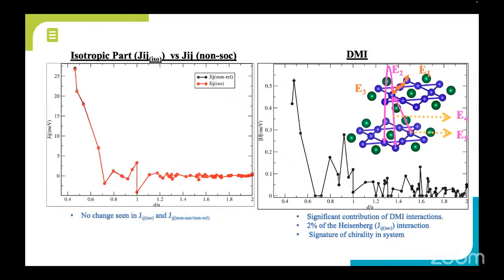With inclusion of the SOC, we see that the isotropic Jij that we evaluated is nearly the same as that from the calculation without spin-orbit coupling. We do not see any difference, but we do see the presence of finite DMI interactions. The value of the DMI, relative to that of the Jij, is very small, of the order of 1 or 2%, which does not favor spin textures in the system, but it shows that some signature can be there if we further induce some kind of changes in the system in terms of doping or strain.